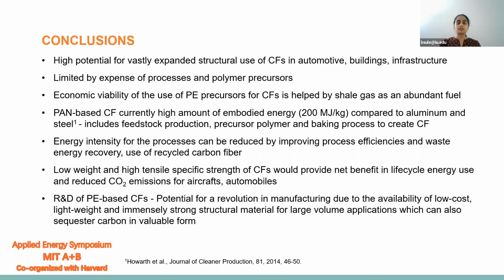Just to conclude, there is a high potential for vastly expanded structural use of carbon fibers in automotive, buildings, and infrastructure. Economic viability of the use of polyethylene precursors for carbon fibers is possible due to the abundant availability of shale gas. PAN-based carbon fiber currently has a high amount of embodied energy compared to aluminum or steel. However, this energy intensity can be reduced by improving process efficiencies and also waste energy recovery.